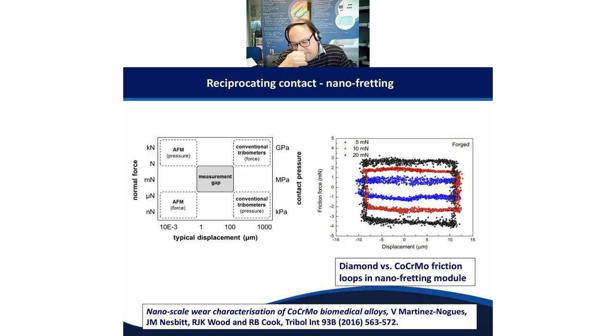These are some friction loops. As the sample is moving back and forth, the sample moves from one direction to the other, we go into a constant sliding period, and then the sample goes the other way, round and round. The area inside these loops is actually an energy, a frictionally dissipated energy. And here we've got friction loops at different applied loads. You can see from this chart we're talking about in the region of 20 micron track length.